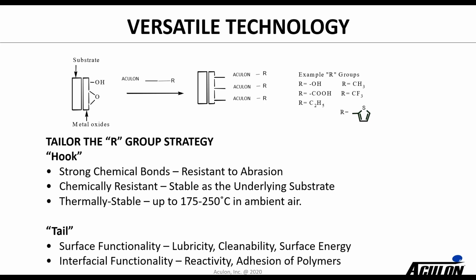What we like to call the R group strategy is essentially the next question after we ask what the substrate is, what's being bound to the surface. Once we know that, whether it's an epoxy or urethane or some other type of treatment, acrylates, we'll choose an R group that's got good compatibility that will react into that resin. We can play this strategy to pick the right functionality, or in some cases we don't always know what's contained in the adhesive, and so we'll just screen candidate R groups and see which one works the best. So this R group, the tail that sticks out, allows us to really tune functionality.